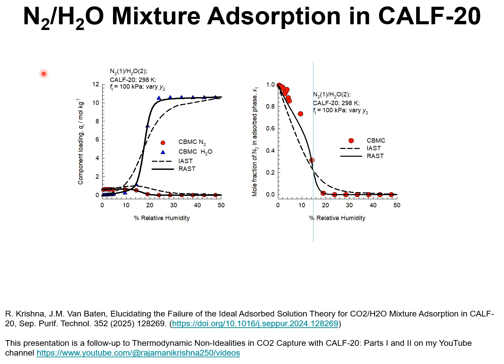Let's examine adsorption of mixtures of nitrogen and water in CALF-20. We conducted configurational bias Monte Carlo simulations for binary mixtures of nitrogen and water at a total fugacity of 100 kilopascals with varying compositions of water in the bulk gaseous phase.